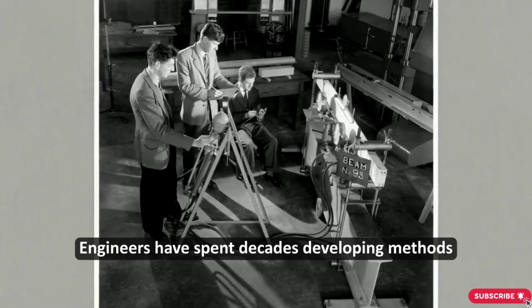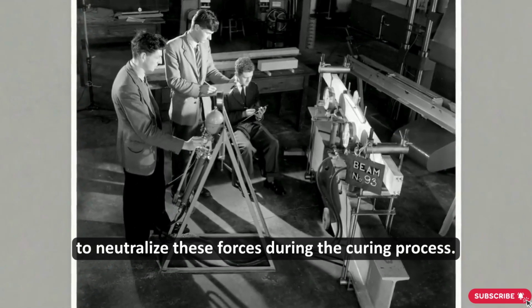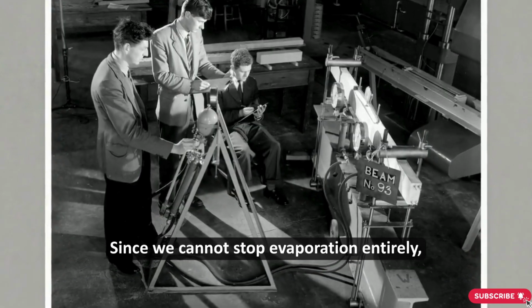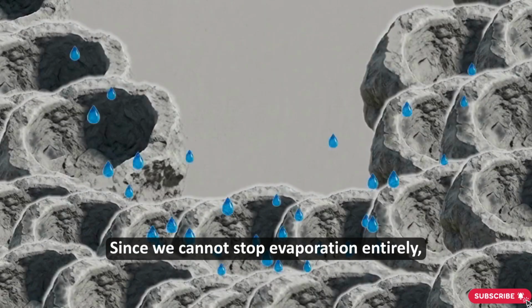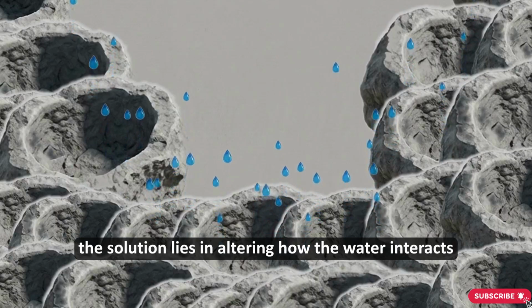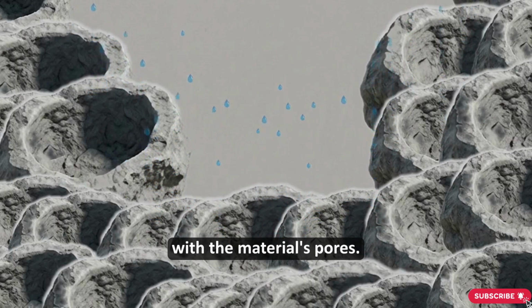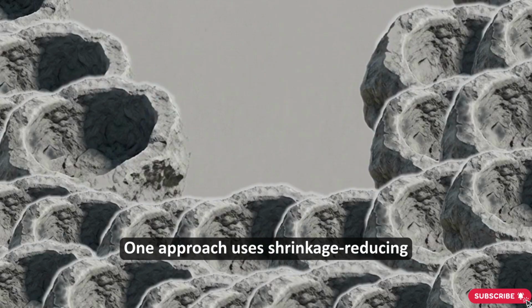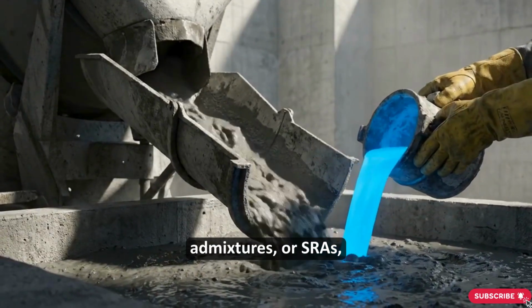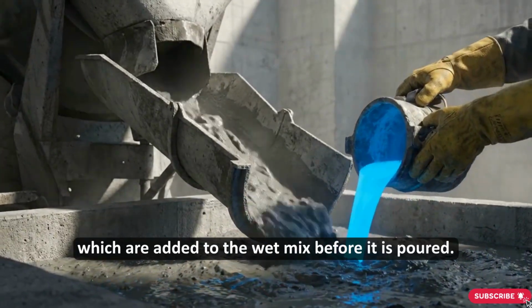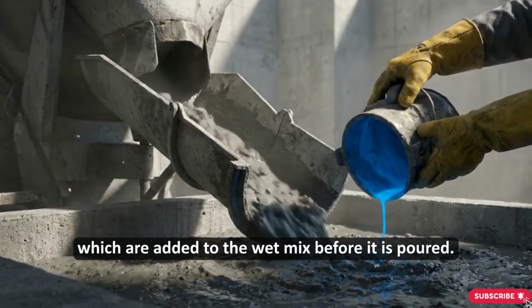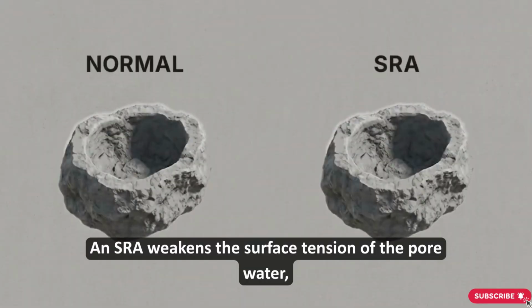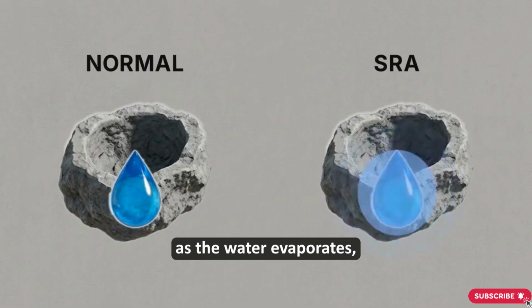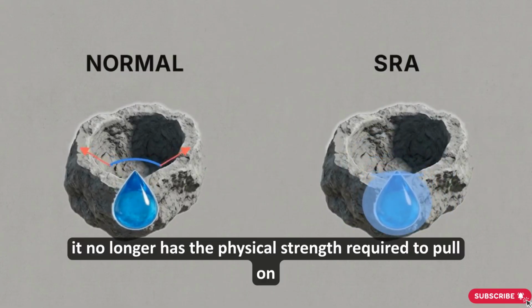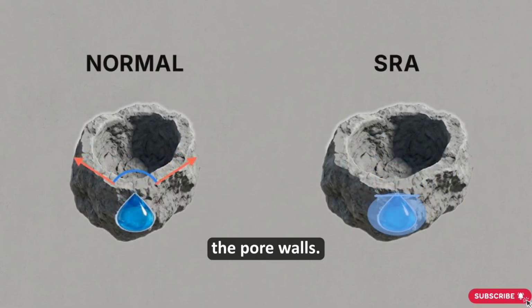Engineers have spent decades developing methods to neutralize these forces during the curing process. Since we cannot stop evaporation entirely, the solution lies in altering how the water interacts with the material's pores. One approach uses shrinkage-reducing admixtures, or SRAs, which are added to the wet mix before it is poured. An SRA weakens the surface tension of the pore water. As the water evaporates, it no longer has the physical strength required to pull on the pore walls.